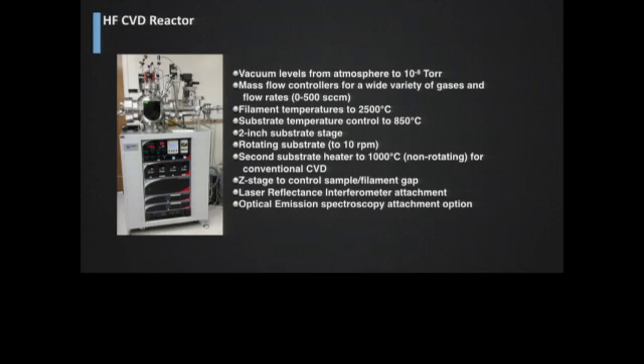We use hot filaments. We use tungsten wires, and we pass a tremendous amount of current through those tungsten wires, and the temperature of those tungsten wires is typically around 2,500 degrees C. The gas passes over them to create these free radicals. The substrate temperature is typically as high as 850 degrees C. Our first version involved a 1-inch, but now we actually have a 2-inch substrate stage. And we also have a rotating substrate, to help with uniformity. And we also have a second stage in this particular reactor that goes to 1,000 degrees C. It's a non-rotating stage, and we were thinking about using it for some conventional CVD inside the same reactor.